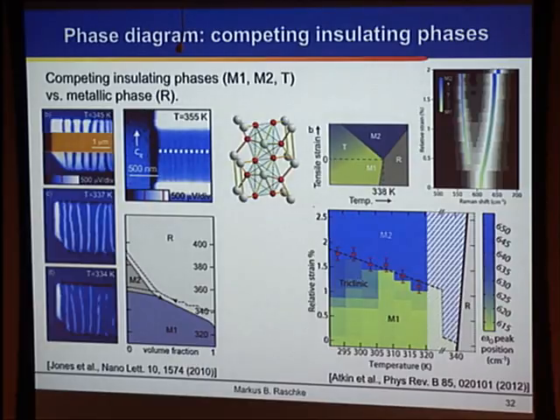Associated with this phase diagram, we can look at the volume fraction evolution of these nanoscale domains as we change temperature, where initially we see the emergence of an M1 phase. Then there is a buildup of internal strain, which starts to stabilize an M2 phase, and then into the rutile phase. And the interesting question is, what would happen if you do an ultrafast pump-induced optical transition, where we optically induce a collapse of the band gap out of this M1 or this M2 phase?